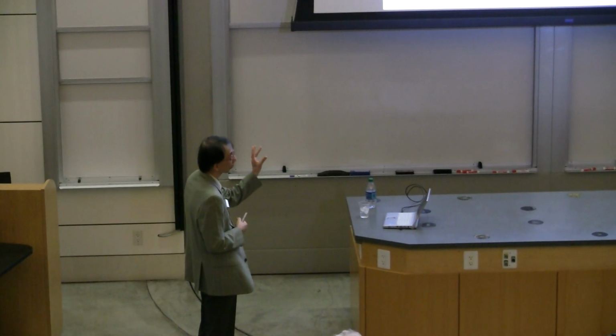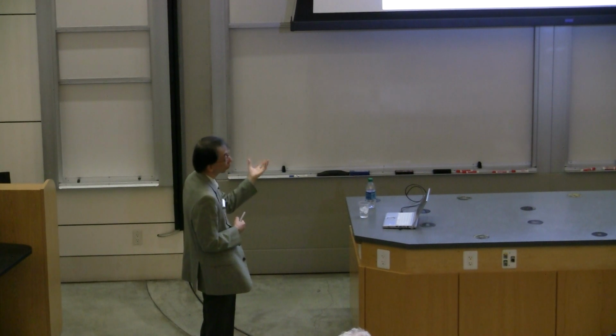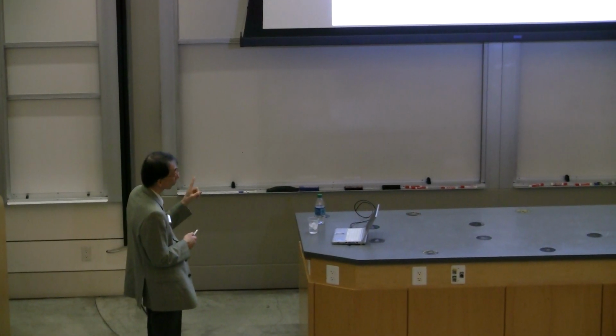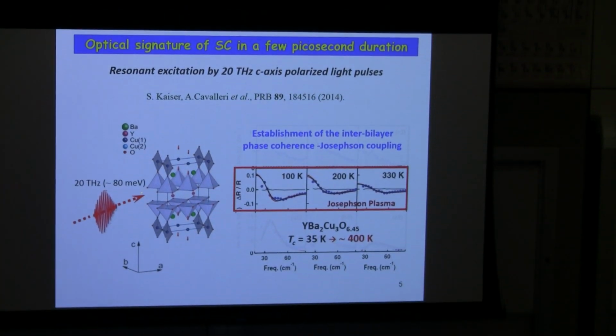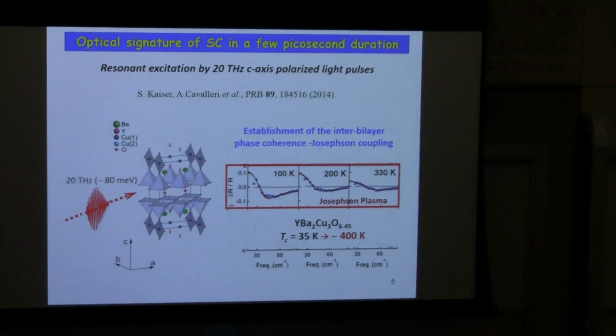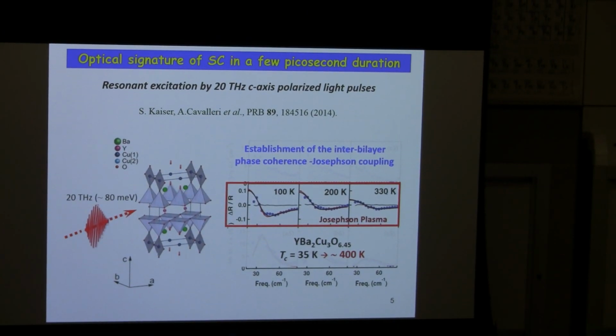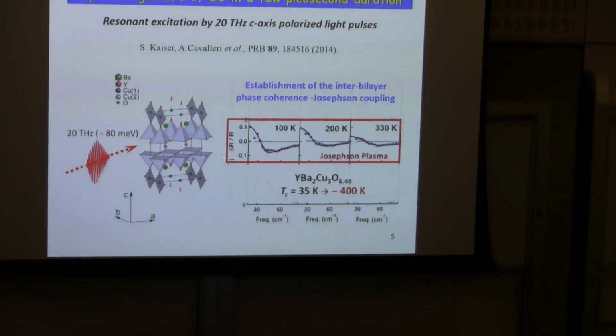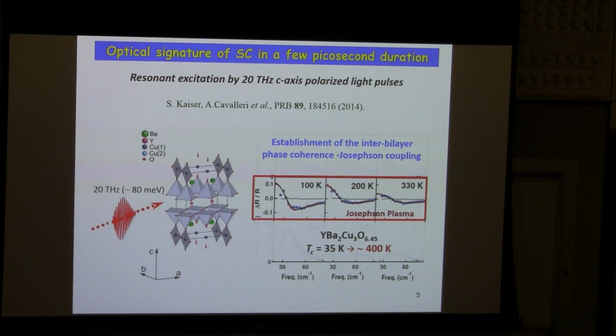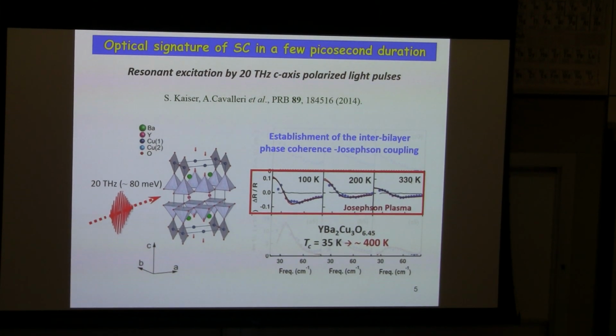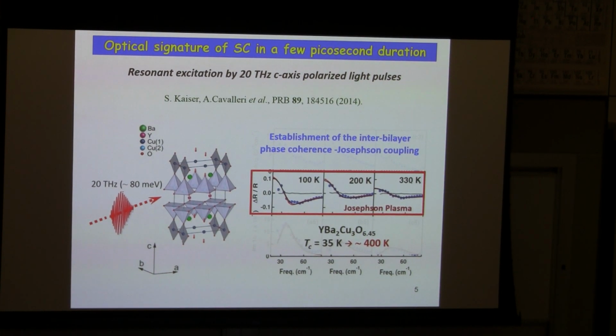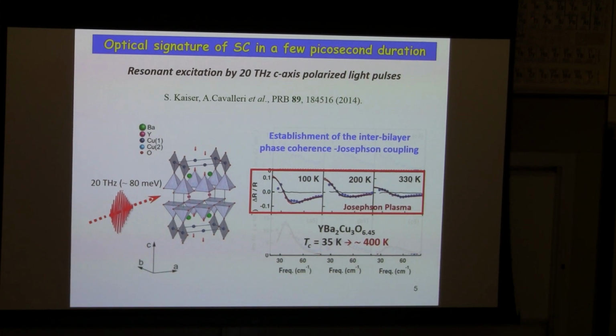Unfortunately, no one knows the exact mechanism why, in this short period, a situation almost like room temperature superconductivity is realized. One initial thinking is that this pump probe is just at 20 terahertz, which corresponds to 80 millielectron volt energy. That corresponds to the eigenfrequency of the apical oxygen vibration. So in the initial stage of this study, these people proposed that the apical oxygen distance gets longer, which is suitable for high TC. But now they never propose such a scenario. I don't know the current situation. Steve, do you have any idea?